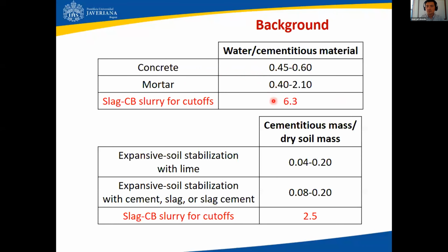However, when we quantify that water to cementitious material, that is including the Portland cement and the slag, for slag CB mixtures, we have a much higher number, an order of magnitude higher, because of the proportions that are normally used during field construction. So it's in the order of 6 or 6.3 water to cement or water to cementitious ratio.